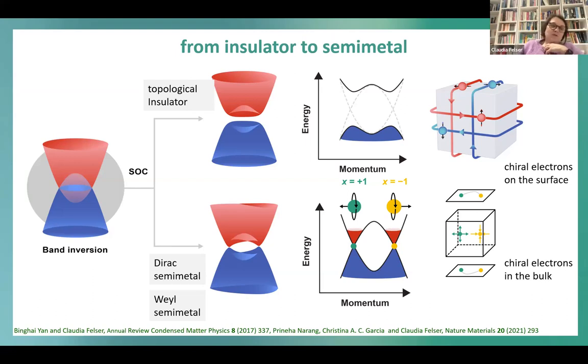And if you draw it in a three-dimensional picture, like you see here on the left-hand side, then the overlapping area is more like a line. This is a so-called nodal line, if you read papers about nodal lines. And you can have a full gap in a topological insulator, and I already explained the surface state. But depending on the symmetry of the crystal, for example if you have rotation symmetries, some of the crossing points can stay connected.